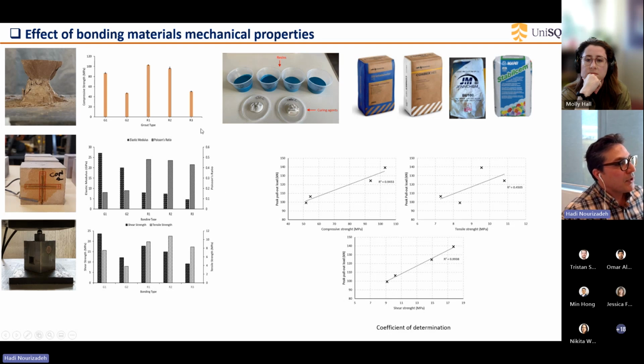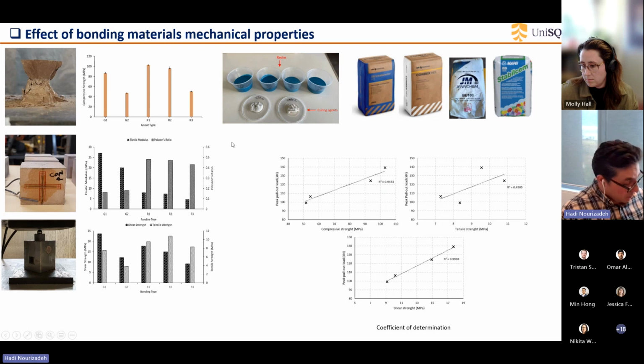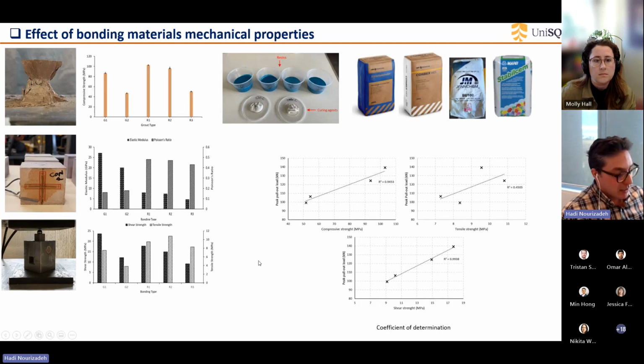By statistical analysis, we found the coefficient of determination, for example between the compressive strength and the ultimate pullout load, is around 94%. For tensile strength it is around 45%. However, for the shear strength it is 99%. This means that the tensile strength of the bonding agent has less effect on the bonding behavior of fully grouted rock bolts. Following up on the previous slide, the shear modulus is the most effective factor.